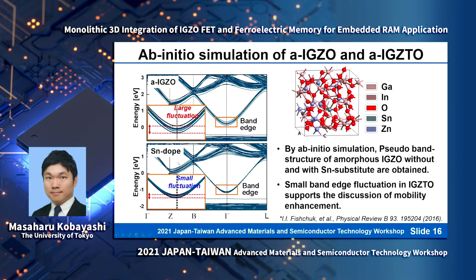for each case. We randomly chose 10 supercells for each case, and simulated a pseudo band structure. And as you can see, compared to amorphous IGZO, a tin-doped IGZO channel has much less potential fluctuation. So this is consistent with our discussion in the previous pages, which is the low potential fluctuation in the amorphous IGZTO channel. So I think this smaller potential fluctuation is the physical origin of the mobility enhancement in the tin-doped IGZO channel material.